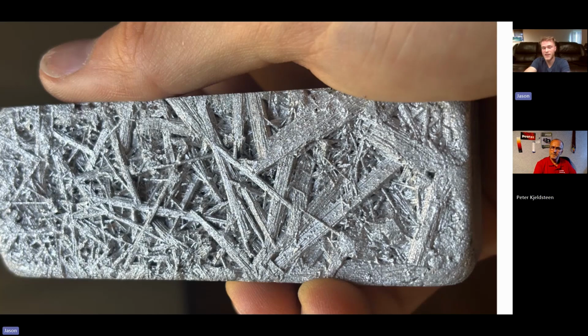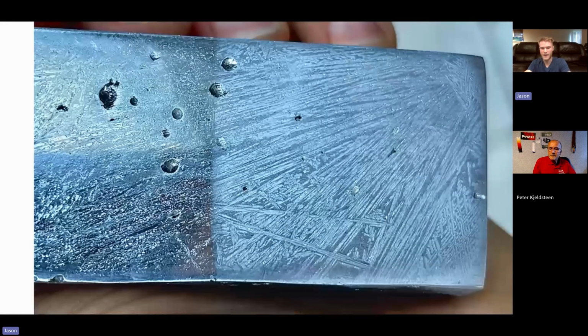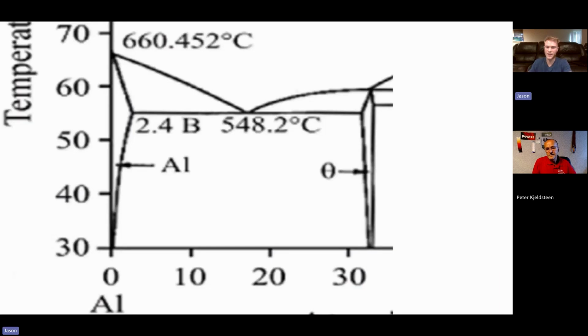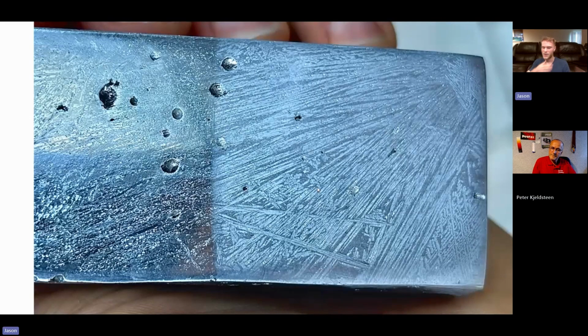But it turns out if you take a face of this and polish it, it doesn't look very impressive. It looks very featureless, and so only the face actually has any features, which is interesting. Moving more left on the phase diagram to get this structure, having less aluminum, points me to the idea of less aluminum being rejected from the solidification, having less constitutional supercooling, and then a more stable growth front for these rods to preferentially form rather than the dendrites. And with this, we see another Widmanstätten-looking structure, that crosshatched region.